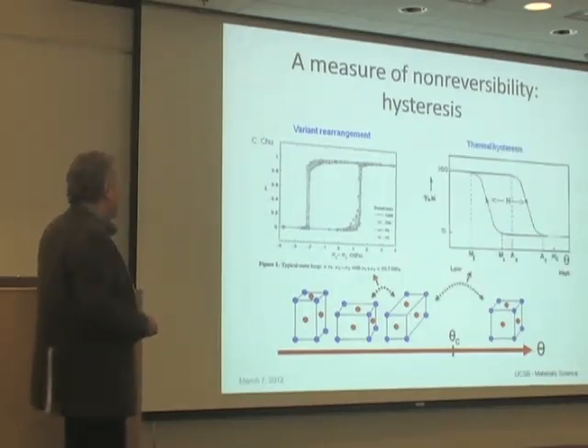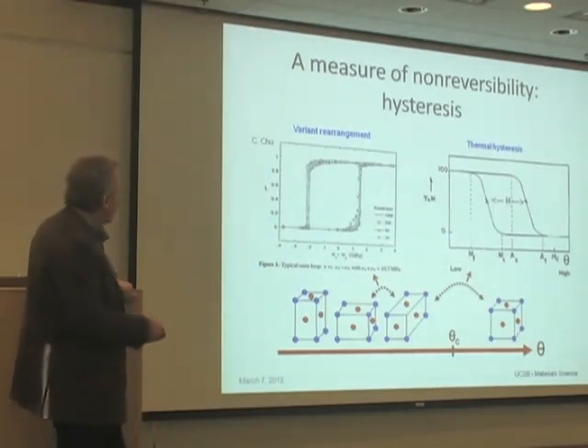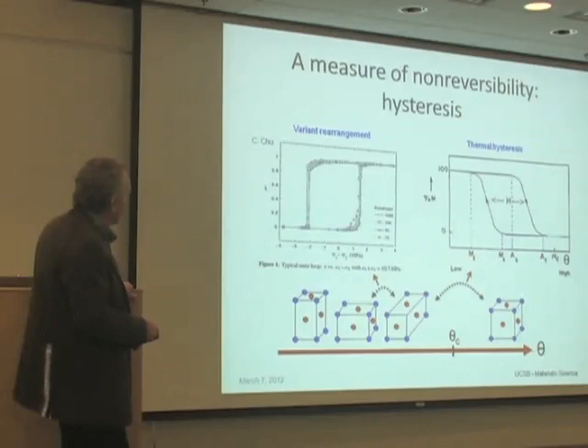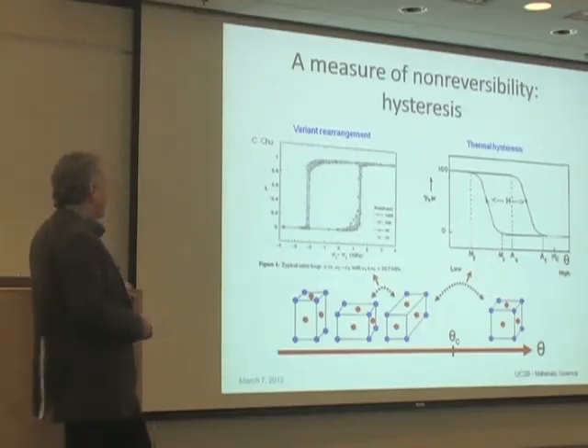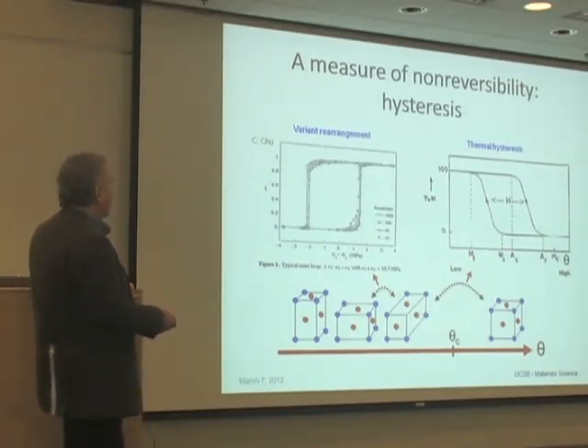So the main subject for the next few slides will be the hysteresis in passing from one phase to another. That's thermal hysteresis. And that has a typical hysteresis loop that might look like that. People usually fit the loop by a parallelogram, and that gives them four temperatures, MF, MS, AF, AS: martensite finish, martensite start, austenite finish, austenite start. That defines the hysteresis loop. So sometimes I'll show you some graphs with those. The width of the hysteresis will be a very typical graph.